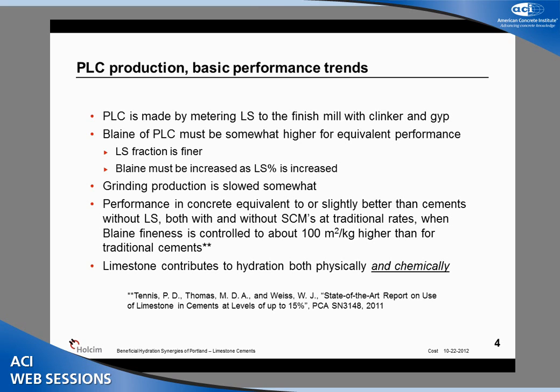But what we find is that the limestone portion of this mixture, since the limestone is not as hard as clinker, is more easily ground, the limestone fraction becomes concentrated in the finer particles of the resulting blend. And so the relationship of the particle character of the limestone and that of the clinker becomes a little bit complex because we don't have a direct test method for evaluating that in the finished material. A lot of the literature summarizes that as long as we grind the Portland limestone cement to a level somewhere in the neighborhood of about 100 meters squared per kilogram higher in Blaine than the comparative ordinary Portland cement, the performance is roughly the same.